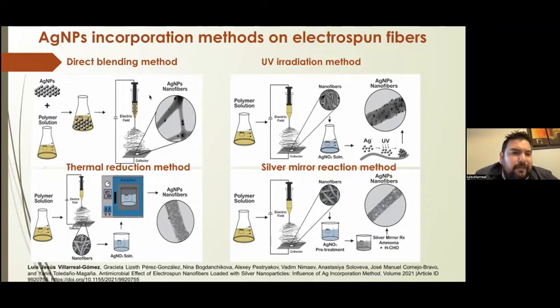The first method is the easy one. You can prepare the silver nanoparticles with another method, and just put them into the polymer solution, and then you do the electrospinning, and you have the silver nanoparticles between the fibers. The main problem of this technique is that you have agglomerations of these particles in the fibers.